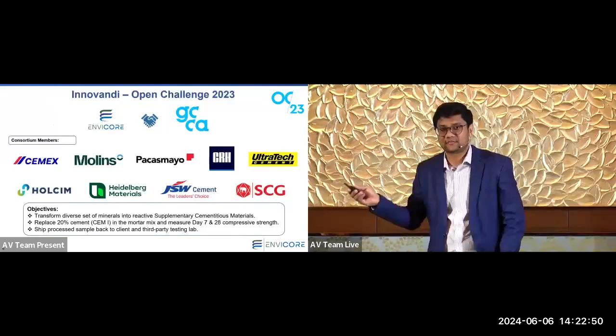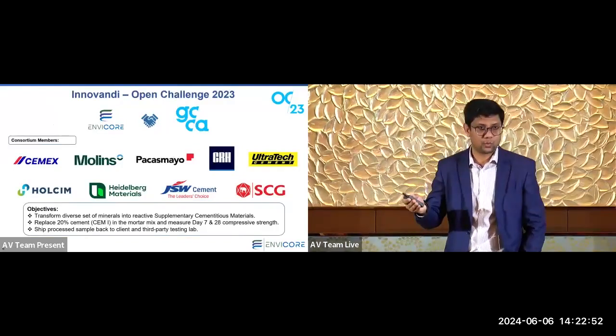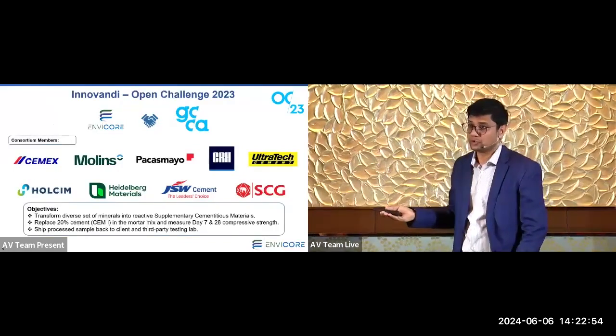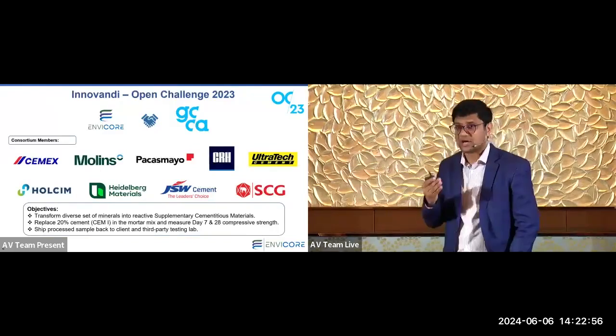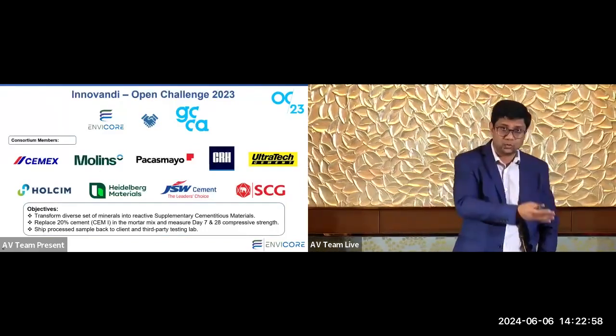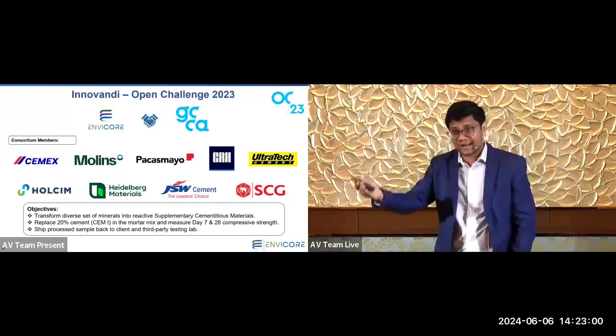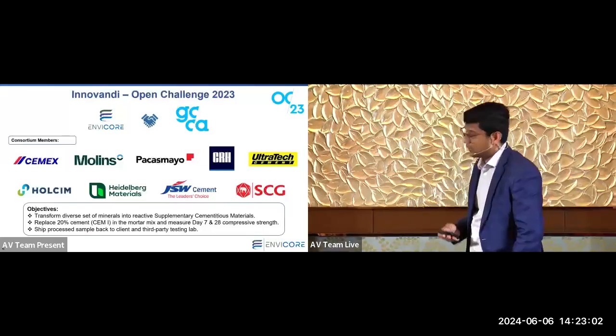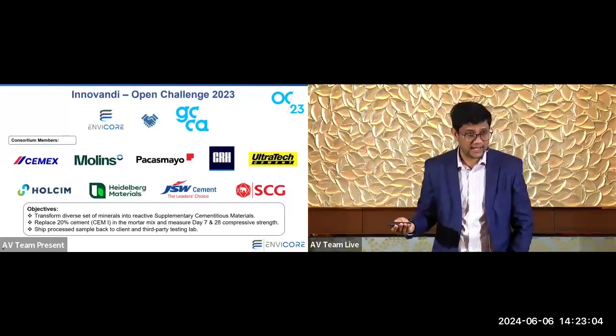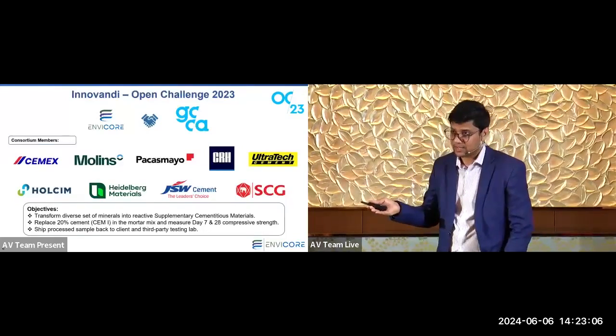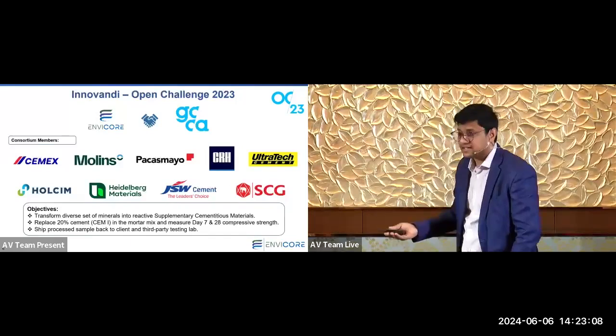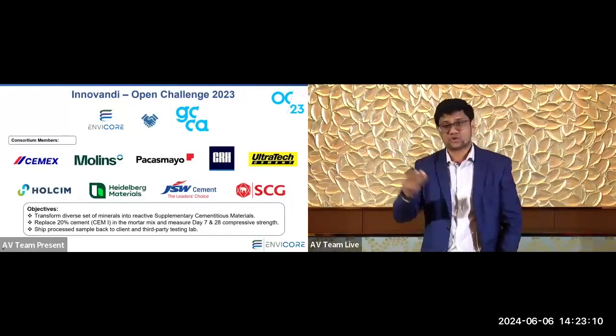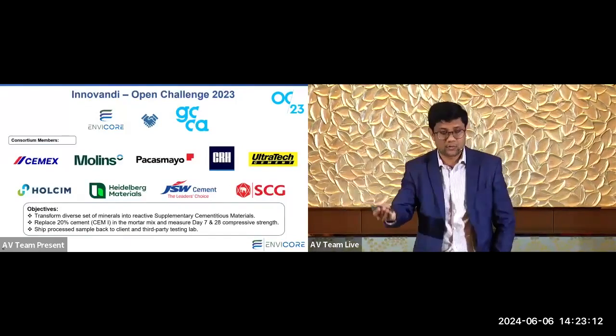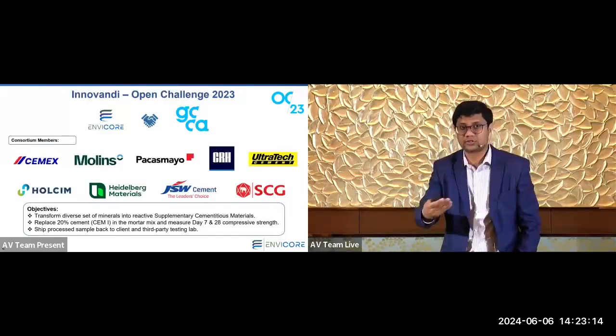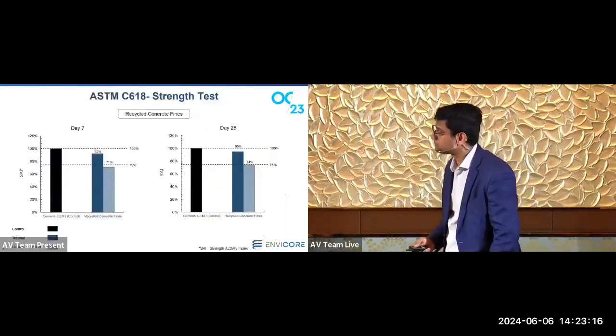But the objective of our consortium was pretty straightforward. We received 12 different mineral streams, and we were supposed to transform them from either low reactive or inert to a highly reactive SCM. We were supposed to do ASTM C618, which is 20% cement replacement in the mortar mix, and basically just send the material back to either third party or technical clients as well for result validation and corroboration.